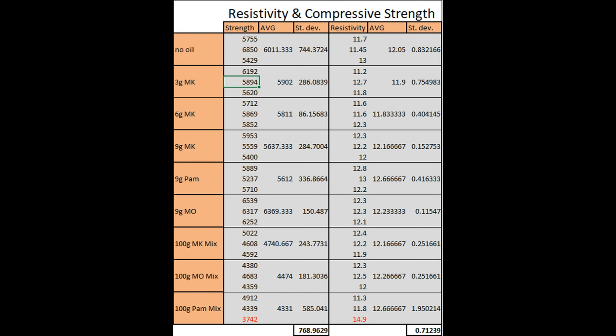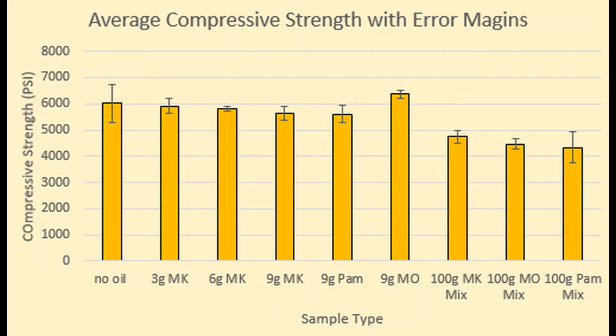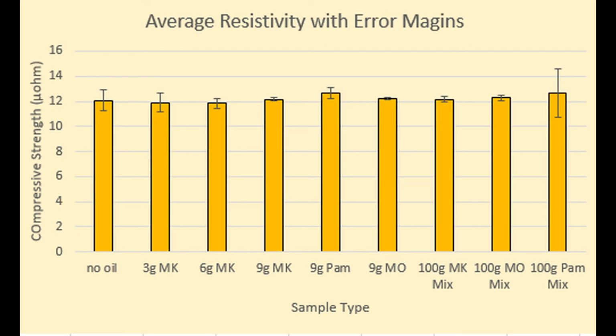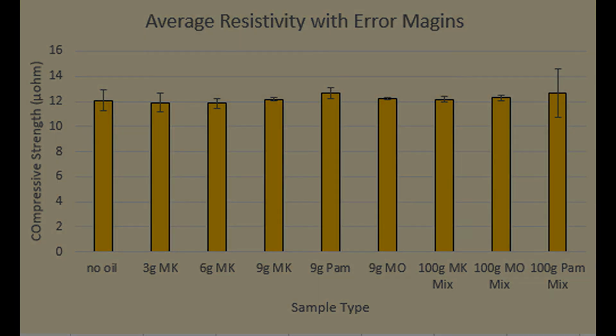As you can see with the samples that only had applications of form oil in the cylinder mold, they all performed relatively equal to one another. But once the different types of form oil were introduced inside the concrete, strength significantly went down, but resistivity stayed the same. These are the samples which had the volatile breaks to them. Very interesting.